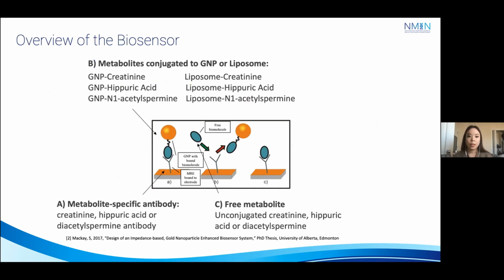So the sensor depends on the attachment and detachment then of the conjugated nanocarriers. And the mechanism by which the gold nanoparticles or liposomes are removed is through a competitive binding system, which has 3 main components. The first being the attachment of a metabolite-specific antibody. So in this study, the creatinine, hippuric acid, or diacetylspermine antibody. And then the second component being the attachment of the gold nanoparticle or liposome attached to the metabolite of interest.